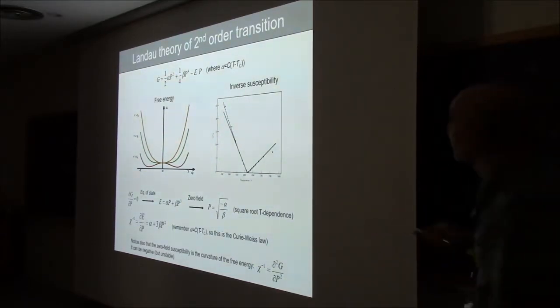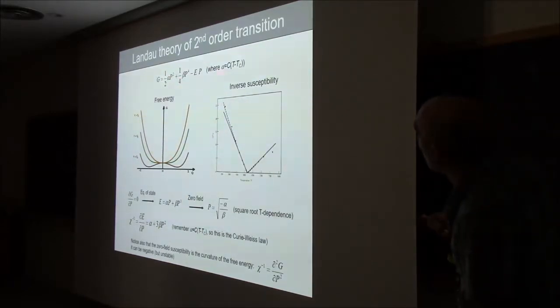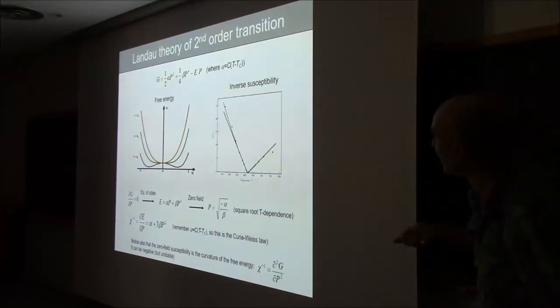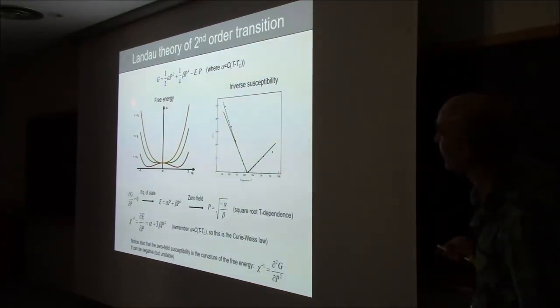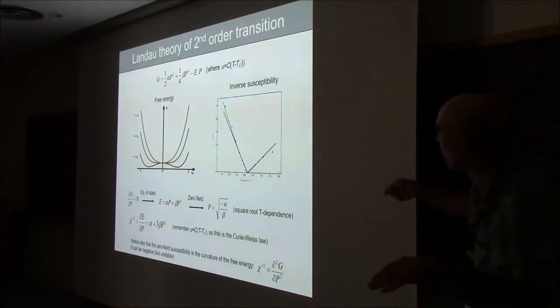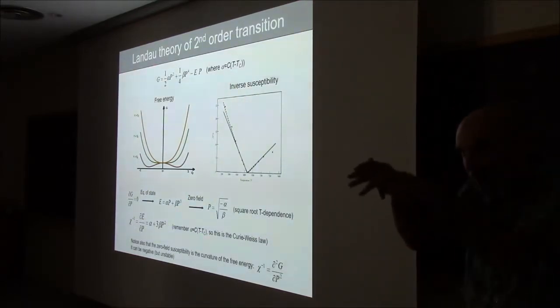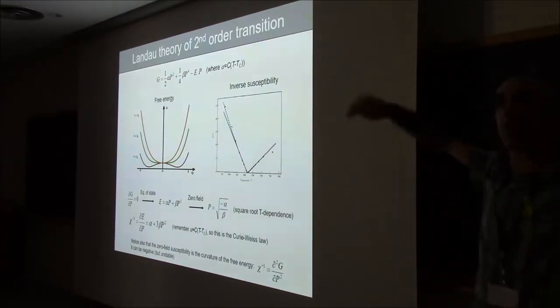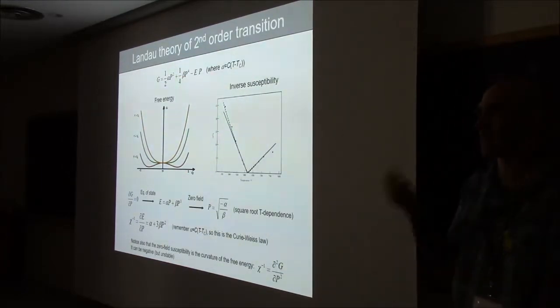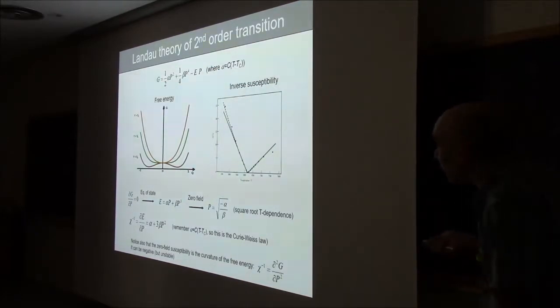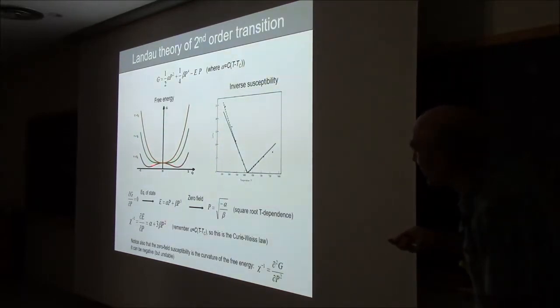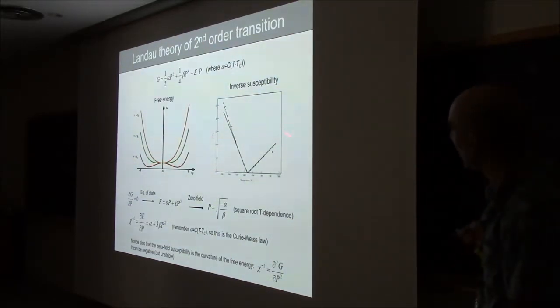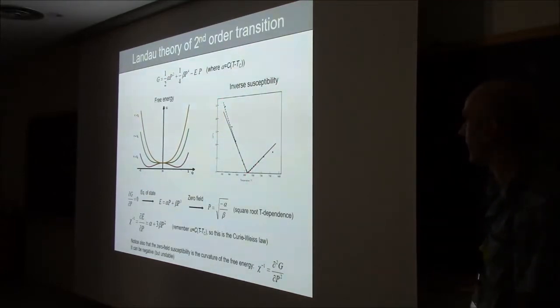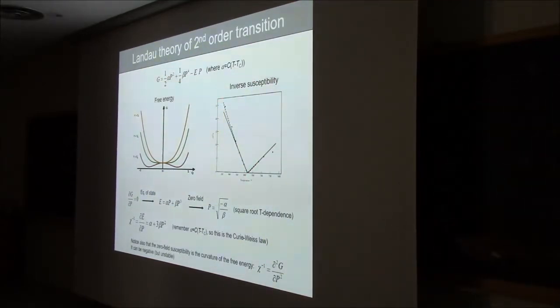Alpha can be positive or negative. If it's positive, then the energy is more or less parabolic, pointing up. If alpha is negative, then for small values of P the curvature is negative, and then eventually when the P fourth term takes over, things become positive again. So you get a double well. That's just maths. In between, if you have a continuous second order transition, you have a state where the barrier between the wells is zero, you have an infinite dielectric constant, and the inverse permittivity goes to zero. You can do the maths of this. You probably already did in university, hopefully.